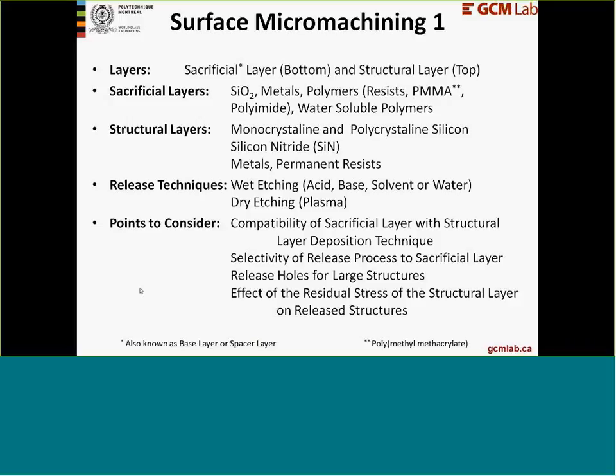Several important points to consider when designing a surface micromachining process. You have to make sure that the sacrificial layer is compatible with the deposition technique to be used for the structural layer. The release technique should be very selective to the sacrificial layer so that the structural layer is not damaged. Very important to provide release holes for large structures to facilitate the release. Otherwise, many difficulties might arise. In the design and simulation phase, we need to consider the effect of the residual stress of the structural layer to prevent undesirable surprises after release.